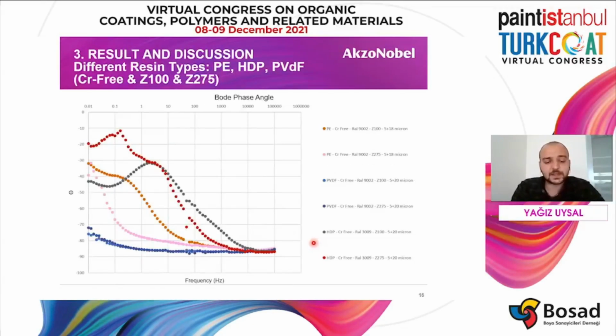And this is the Bode phase angle diagram of all 6 samples. As I mentioned before, in the phase angle graph, it's important that samples have a minus 90-degree angle. And if you look at the results, the 2 PVDF coatings, with zinc layer amounts of 100 gram and 275 gram, are reaching minus 90 degrees at low frequencies compared to the other ones. And polyester coatings are following the PVDF, and the other one, the high durable polyester, is the last.